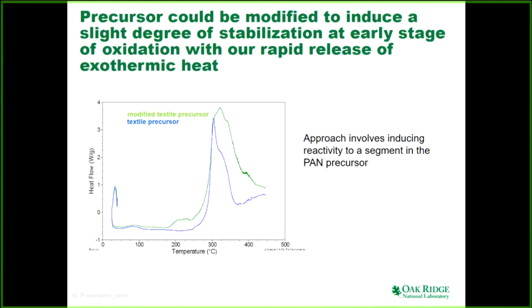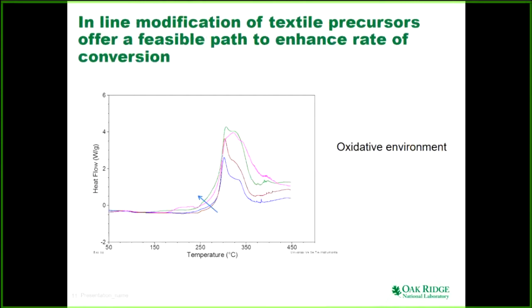And then let us see, we formulated different compositions and we validated with that. And now I would like to mention that these technologies, whatever we have developed, don't necessarily need a particular co-monomer. As long as you have a certain constant mole percent of polyacrylonitrile or acrylonitrile, it should work, and it works. So if you have a different co-monomer, whether it is acrylate or acetate-based, all those are esters, it doesn't matter. It works because it affects the acrylonitrile fraction and it does the reaction.